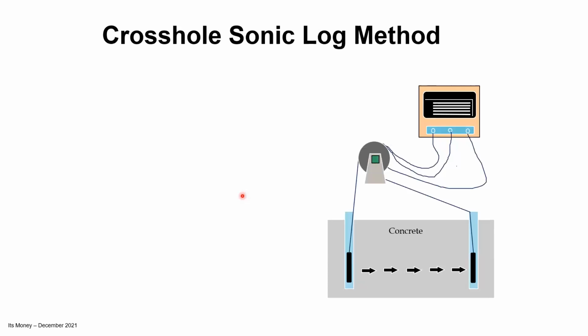And a cross-hole sonic log method, it's usually in tubes that are pre-placed or precast in the concrete, but it can be used in core holes in an existing structure. It's been used to evaluate dams, mass concrete foundations, and large diameter drilled shafts in this form. A transmitter and a receiver are lowered down adjacent boreholes, and the transmitter emits an ultrasonic pulse that travels through the concrete to the receiver.